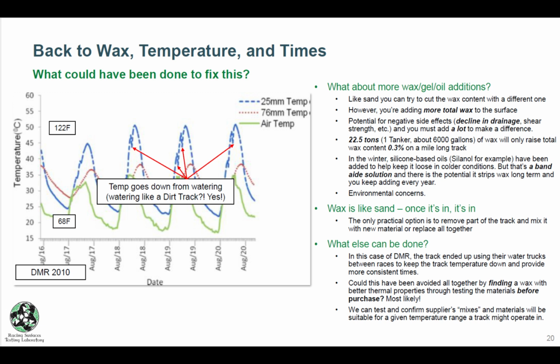In the winter, to keep the track looser and from separating out, I've heard of Silanol being used, which is like a silicone-based oil, and that's been added to help keep the track looser in colder conditions. But it could potentially be a band-aid solution, because when you add oils to a racetrack, there's actually the potential for the oils to strip the wax out of the racetrack, because it's dissolving the wax. And then when you have rain come through, it can start washing that material out. And I have evidence supporting that. And then, of course, that causes the environmental concern of you losing material through your drainage.